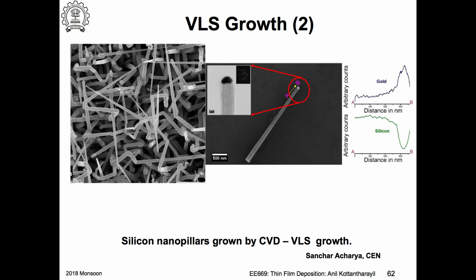Okay. So if you take one of these nanowires and do a high resolution SEM imaging, you find this. This is a nanowire. Basically, you put it in water and then shake it, so these nanowires will break. You can take that water and disperse it on some substrate and then evaporate the water. So you will actually get these nanowires here and there. And this is an image, and you can see here a very long nanowire.